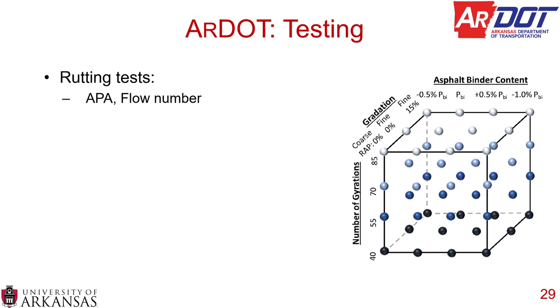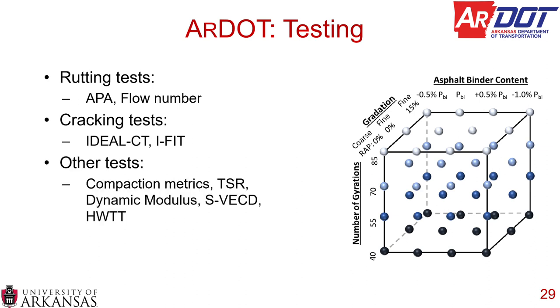That's a pretty cool figure, if you ask me. But for testing, for rutting tests, we're going to look at the APA, which is ArDOT's current rutting test, and the flow number. For cracking tests, we currently don't have a cracking test in specifications. We've done some preliminary work with Ideal CT, but we're going to run both Ideal CT and iFit, because I personally believe that iFit is one of the more popular cracking tests being used, especially at the intermediate testing temperatures.